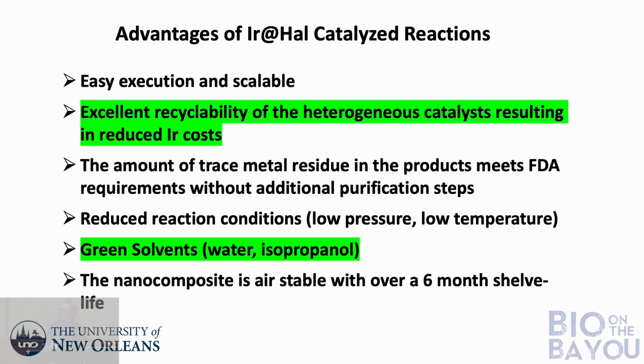Water is ideal. And of course, with regard to our iridium system, we can run these at low temperature and low pressure. The nanocomposite itself has a long shelf life. We've looked at it sitting on the shelf for about 6 months, and it recovers without any loss of activity.